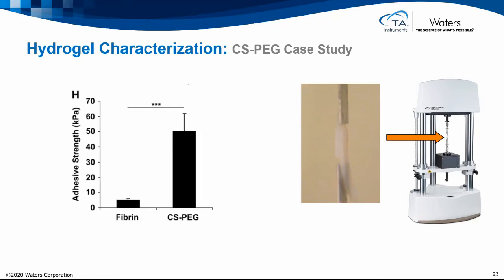Then you pull them in the shear direction, in this case up and down, and you measure the maximum force. You can convert that to stress and look at the adhesive strength. So that's how that test is done. On the same instrument, similar type of force, probably higher forces than we did with that low force load cell, but to measure, in this case, the final result. Having tuned all those other properties, you get the primary advantage: using the additional properties of this biologic material combined with the hydrogel to create better bonding in this tissue, a better adhesive joint.